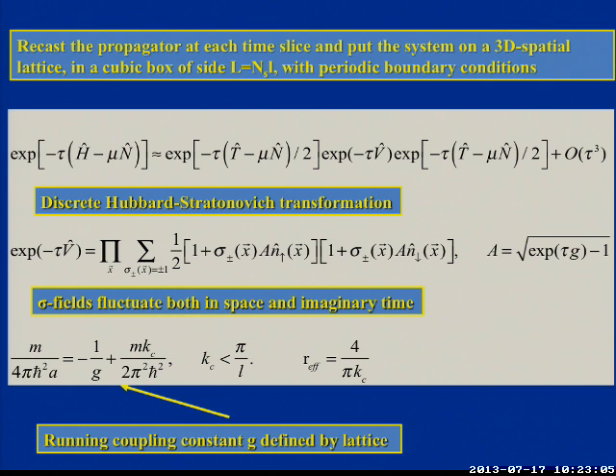And if the lattice is large enough, I mean the box is large enough, that correction is exponentially small. So I hope that settles. Okay? So these are the two aspects there. So this is actually continuum with finite cutoff momentum, not go all the way to infinity. But you put it in the lattice, there is a correction which depends on 1 over L, which is the size of the box. Okay?